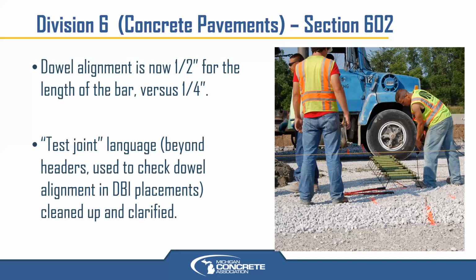And they implant dowels instead of the plastic tubes or sleeves in that test joint. And it's a destructive test because they have to then expose the dowels to verify the alignment of the dowel bar inserter. And so that language in the spec is simply clarified and simplified because that was getting interpreted differently. And so they wanted some more direction to their field staff as far as being a similar process used throughout the state for that verification of the dowel alignment on a dowel bar inserter project.